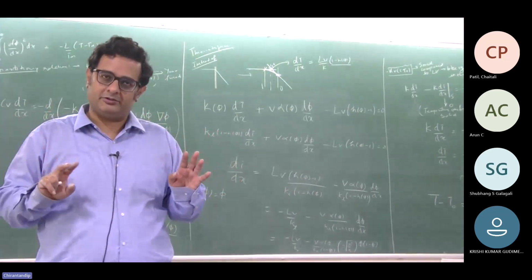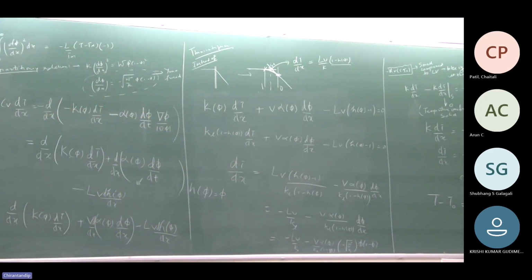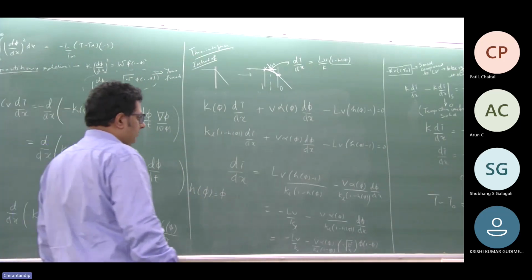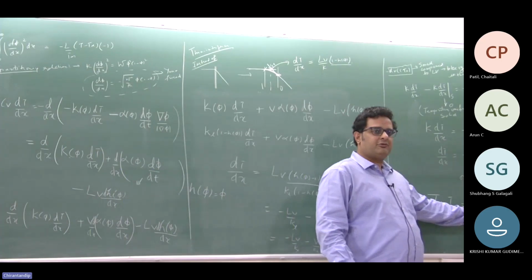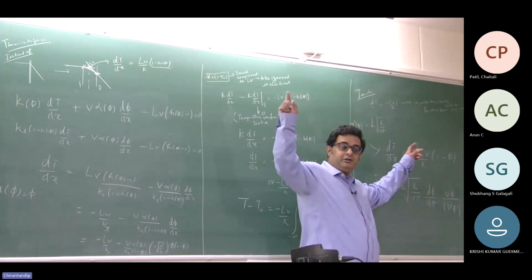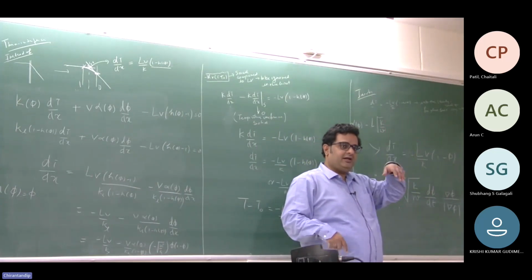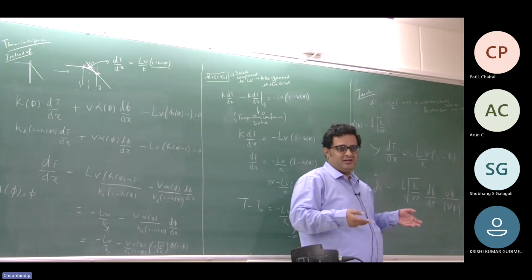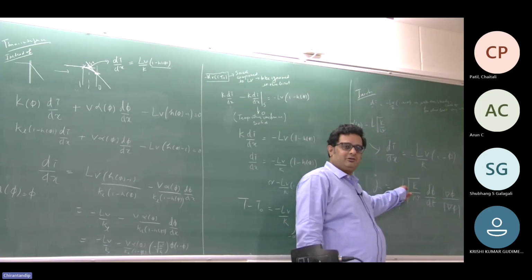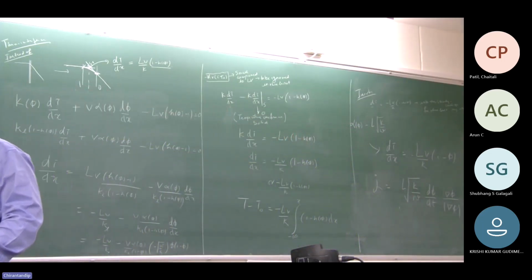So the equilibrium is also changing because of this, over time. This anti-trapping current will also automatically be adjusted. Typically in this particular case, it's just delta K. For the alloy case, it will be delta C, as you saw in the equation where we derived it, that is delta C, CL minus CS, and CL minus CS changes. So you put CL minus CS over here and take care of it. That's as simple as it gets.